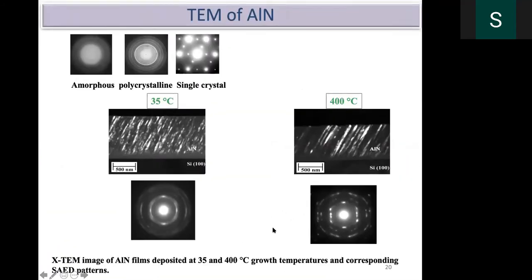Well, I wanted to compare the transmission electron microscopy profile of the film grown at 35 degrees, close to room temperature, and this one at 400 degrees centigrade. You can see almost all orientations exist in one, and in this case, it's one particular orientation. You can understand that difference from this.